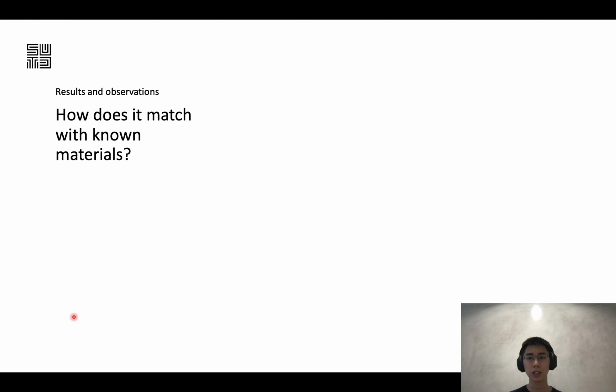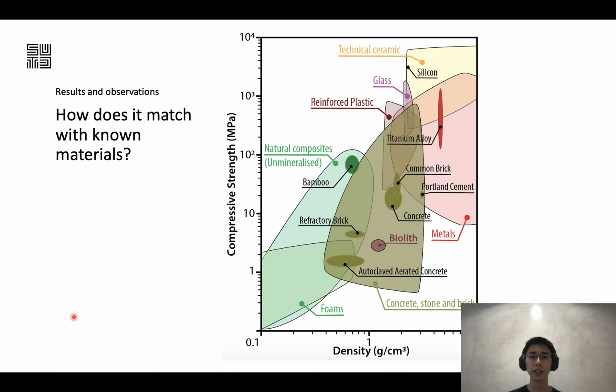Now, as you can see from the previous result, the mechanical strength is about 2.5 megapascal in terms of compressive strength. Now, how does that match up with the known materials? Just to put things into context. Now, we plotted this in an Ashby plot, and we find that it's actually closer to being a brick rather than a concrete. And actually, the compressive strength is slightly lower than the brick.